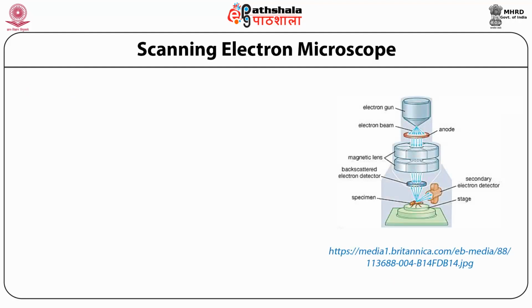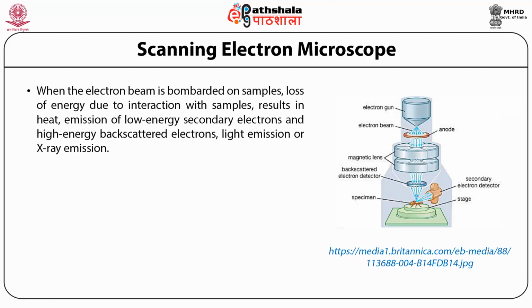Scanning electron microscope. Similar to TEM, the scanning electron microscope is another variant of electron microscope in which an electron beam is used to illuminate. However, instead of looking at the transmitted light, in this case the scattered light is used to generate an image of the sample. When an electron beam is bombarded on a sample, the loss of energy due to interaction between sample and electron beam results in heat, and the emission of low energy secondary electrons as well as high energy backscattered electrons. These electrons carry information about the sample and its composition in terms of structure and topography, and this information is captured to generate a three-dimensional image.